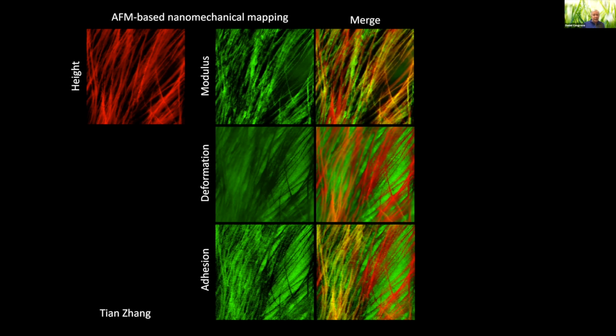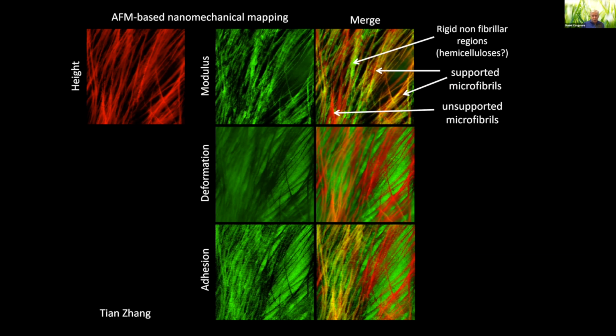And by combining these different nanomechanical maps with the height map, we can learn some things. For example, we can see regions where the microfibrils are supported. They don't deform as much to the indentation with the AFM. There are other regions where the microfibrils deform quite a lot, so the underlying matrix is not supporting them. We can also see non-fibrillar regions.